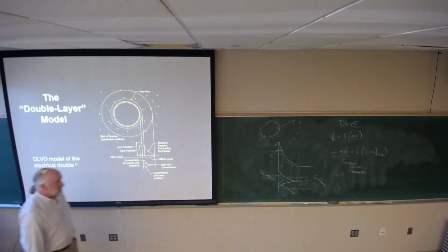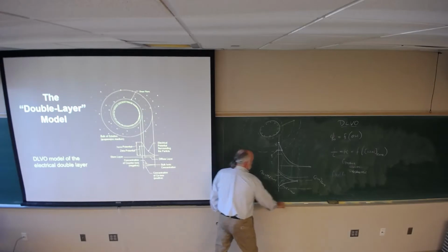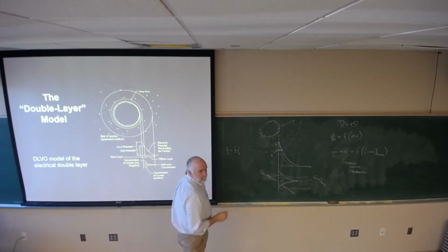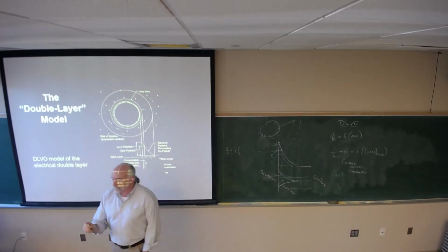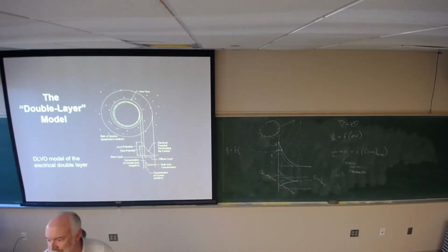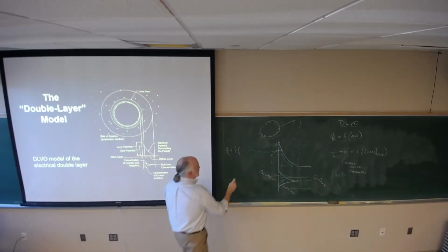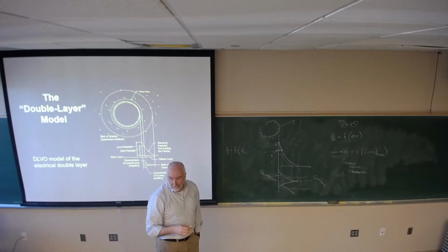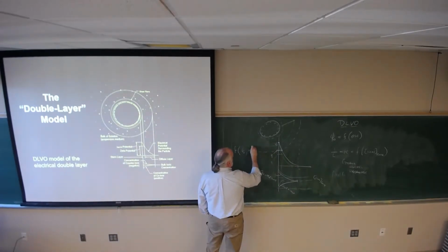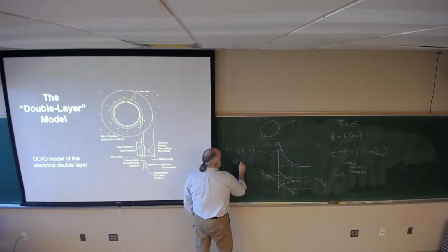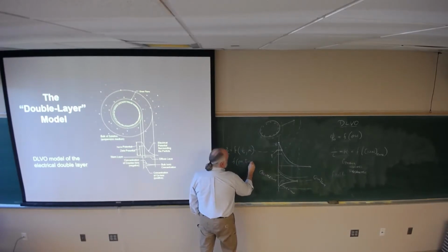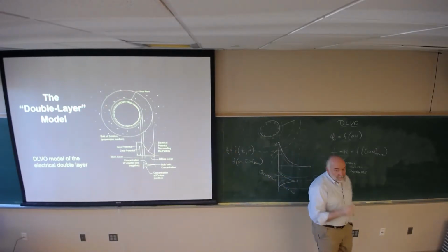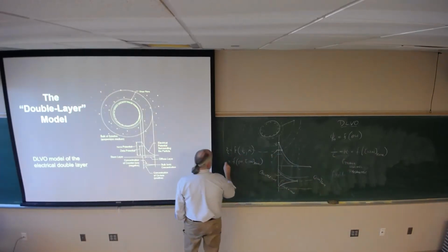So that means that we have zeta potential as a function of 2 things. Zeta potential is a function of, give me one. Okay, and from that we get the Nernst potential. And the second is ion concentration, and that gives us the Debye-Huckel parameter. Okay, so you could look at it this way, a function of pH and concentration of ions in the bulk. Good? So the zeta potential is a function of both of these things.